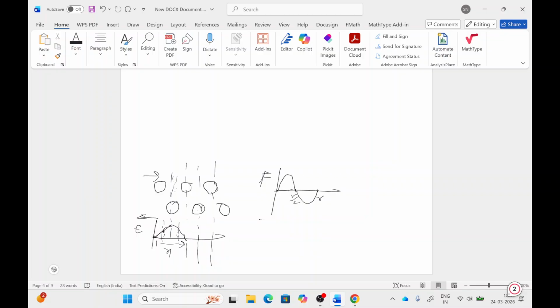We can write force as shear stress tau, which is directly proportional to sine of this r. If we calculate it, there is some derivation, and the energy curve follows like this. This results in the Peierls stress formula: tau Pn equals 2G divided by (1 minus nu), exponential of minus 2 pi w divided by b.